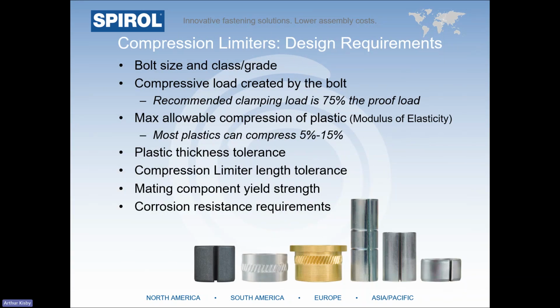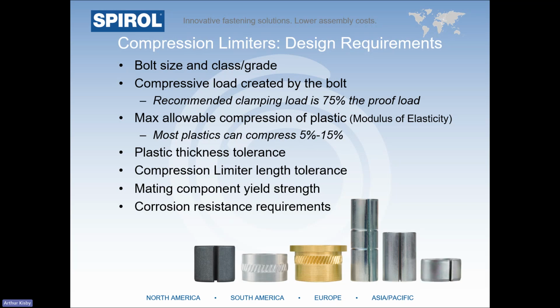So now, to tie in the rest of the information we require when making recommendations for compression limiters that we just reviewed. We discussed bolt size, class, and grade, compressive load created by the bolt, and talked about the clamping load being 75% of the proof load. We have the maximum allowable compression of the plastic, known as the modulus of elasticity. Most plastics can compress between 5 and 15%. Plastic thickness tolerance, compression limiter length tolerance, mating component yield strength, and corrosion resistance requirements.